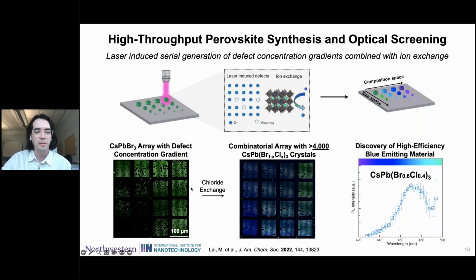And so you can see these optical images on the bottom after irradiating with the laser, where we see the defects are causing a loss in fluorescence. And as we introduce chloride, we regenerate the fluorescence, but the extent of chloride now changes the color. And so we can use this to discover materials that have a good blue photoluminescence, which is very important for making blue LEDs, for example. And so you can plot on the bottom right this wavelength versus intensity plot and find which material has the highest intensity for blue emission.